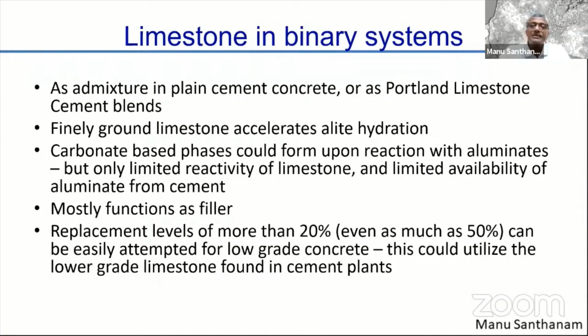Now, the interesting part is only a part of this carbonate can actually react because very little of the limestone actually dissolves in the solution to start reaction. As a result, most of the limestone that you add in cement remains as a filler. It needs a good source of reactive alumina to really harness its potential. And that's where this limestone calcined clay becomes a highly advantageous proposition. Now, if you go for more than 20% replacement, you do have an opportunity to use much higher levels, up to 50%, as I said, in low-grade concretes without any problems of compromising the strength or long-term performance.